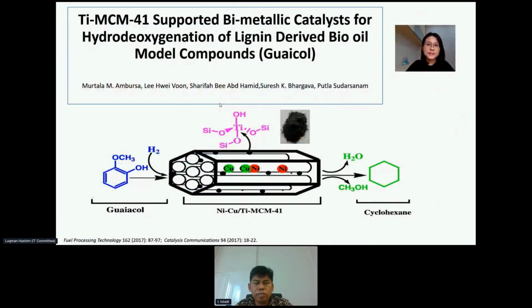Here come our research findings. This study utilized a lignin-derived bio-oil model compound, guaiacol, for the production of cyclohexane, which is one of the compounds in high demand in the chemicals and fuel market. The hydrodeoxygenation reaction is the main reaction pathway in the presence of hydrogen gas. The catalyst developed here is bimetallic nickel-copper supported by modified mesoporous silica, in which titanium is doped on the MCM-41 support. The advantage of this catalyst is that the titanium dopant can help to improve the acidity, both the Lewis and Bronsted sites of the catalyst support, and provide redox active sites for the reaction as well.